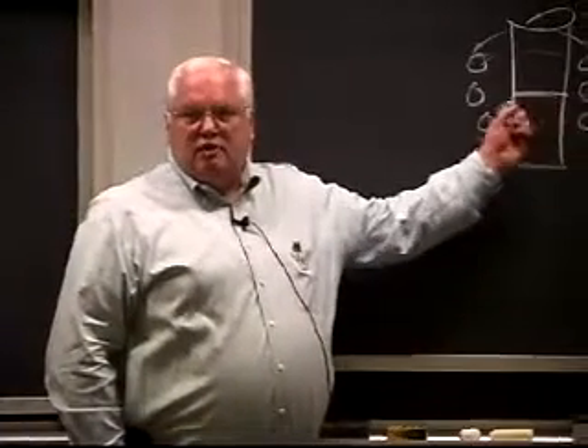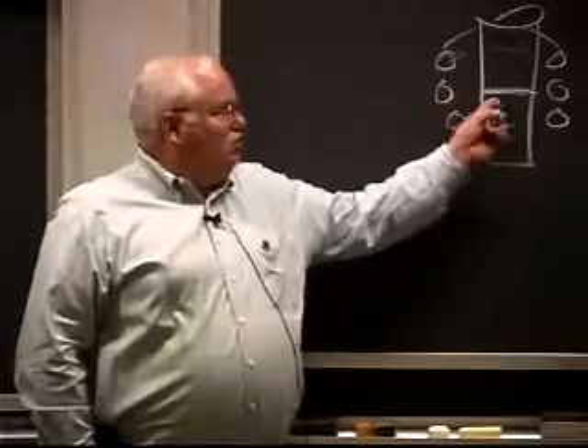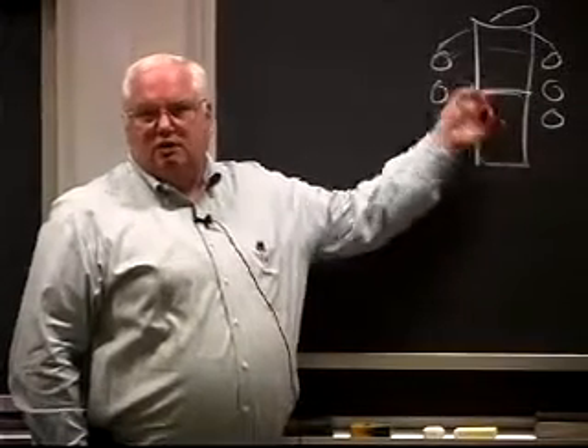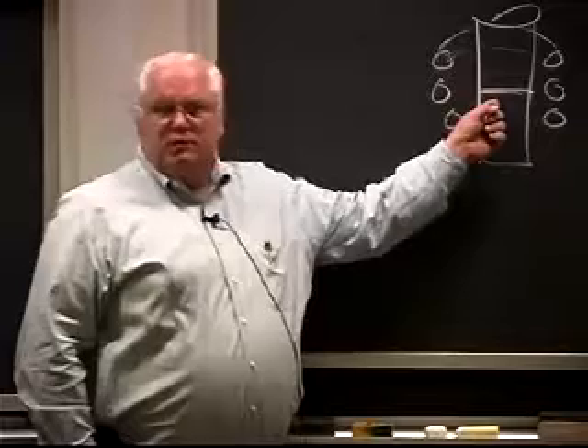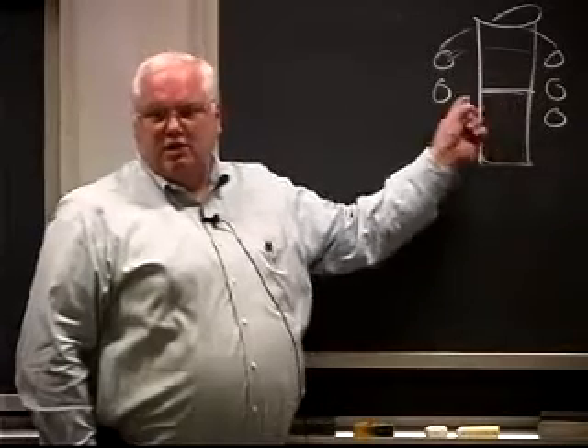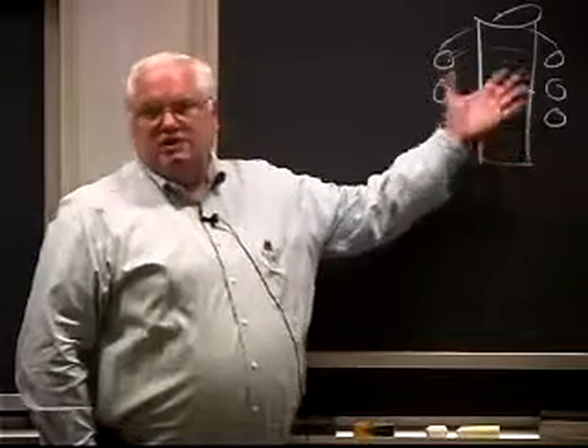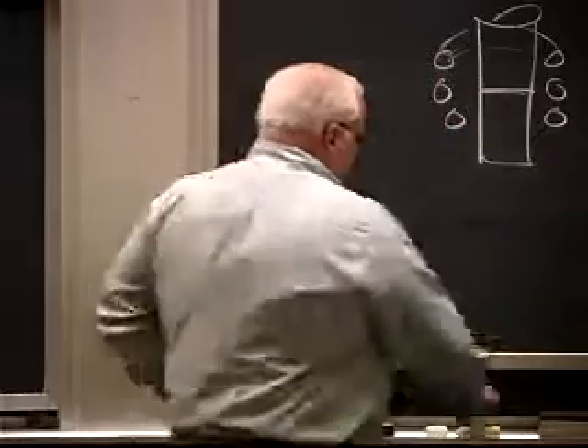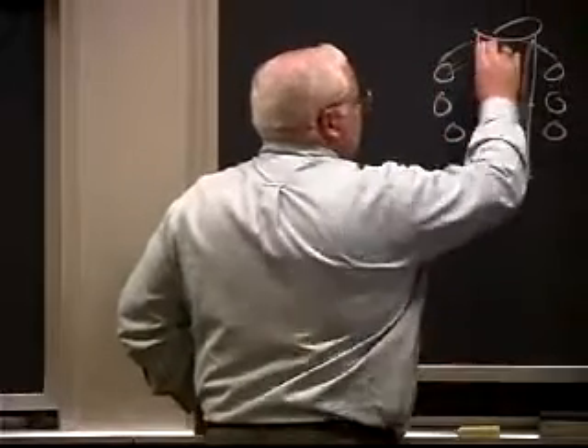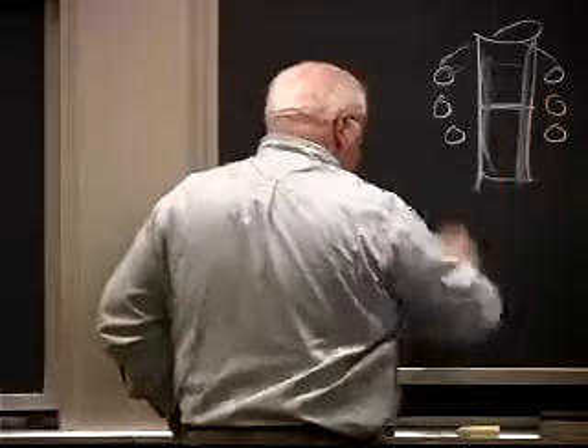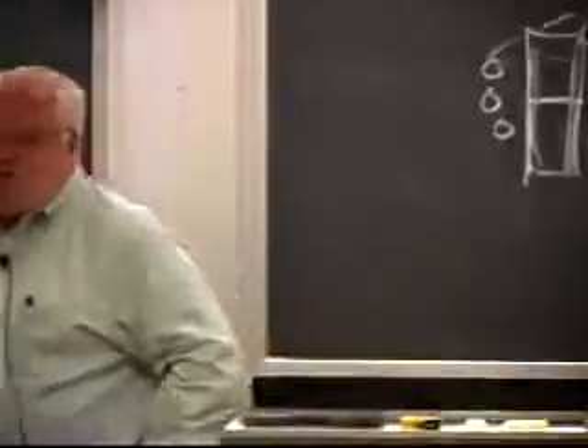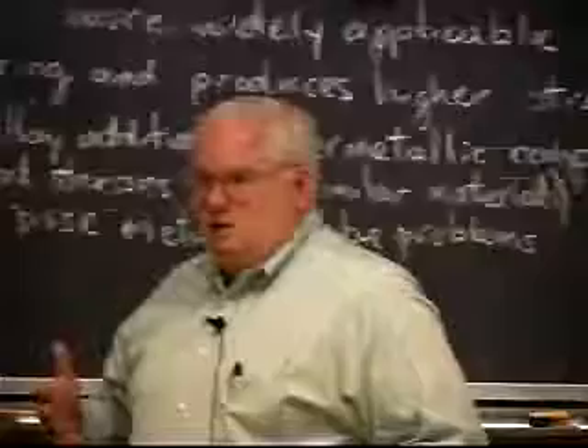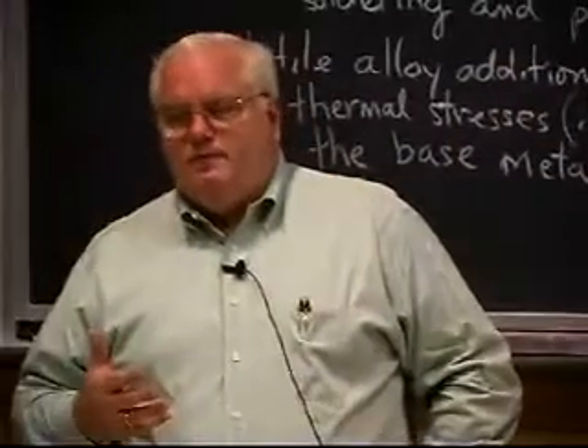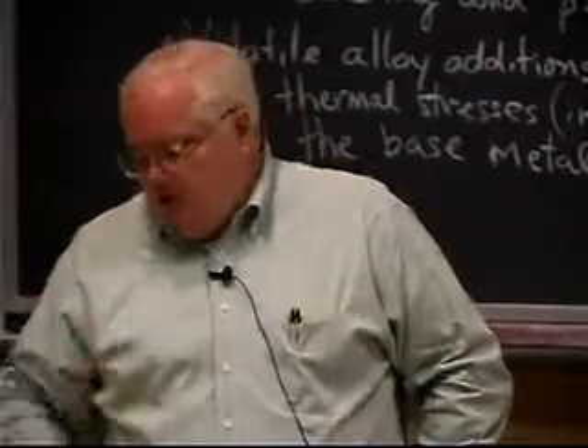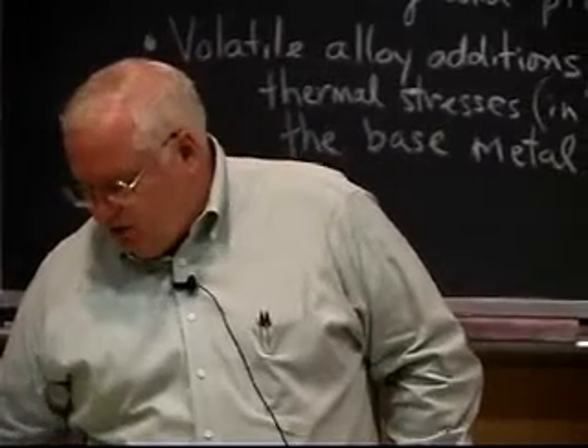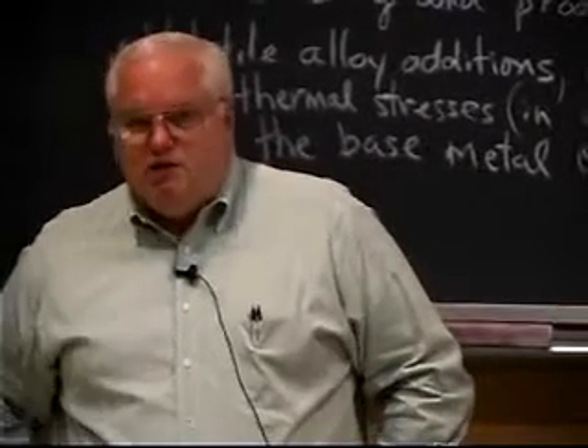The oscillating magnetic field will induce, that's why we call it induction, a current, eddy currents, in the metal. So you have this oscillating magnetic field in the presence of a conductor generating currents. The currents in here resistively heat the metal, except they do preferential resistive heating on the outside surface of the metal rather than in the very center. And so sometimes you might use induction heating because you want greater heating on the outside rather than the inside, for some reason on your part, to control the way the braze flows or whatever.